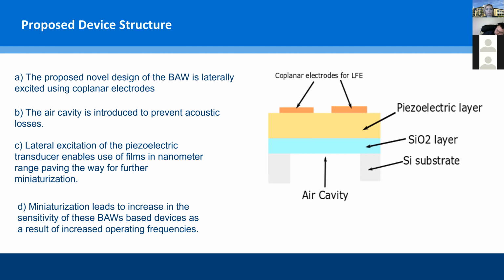So here is the proposed device structure that we used. We have a coplanar electrodes arrangement, and then we have a piezoelectric layer beneath it. Then we have a silicon dioxide layer, which acts as a passivation layer to prevent the acoustic losses. And then we have an air cavity to prevent the acoustic energy from getting radiated into the substrate. As I discussed, this bulk acoustic resonator design is laterally excited using the coplanar electrodes, and the lateral excitation results in the miniaturization of this device, which could enable us to get higher operating frequencies.